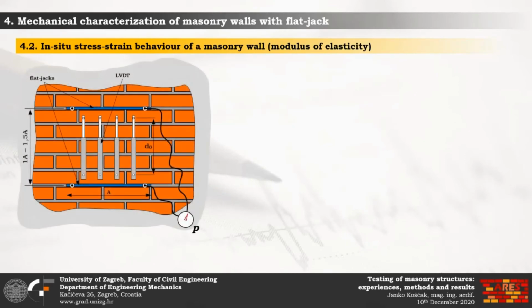Secondly, in situ stress-strain relationship behavior or modulus of elasticity can also be determined using the flat jacks. The procedure is shown in advance. Firstly, 2 flat jacks of a width A should be placed into the horizontal masonry joints, one above the other, at a vertical distance of approximately 1 to 1.5 A. In addition, the space between the flat jacks should consist of at least 5 layers of bricks, also as shown in the figure, and the flat jacks should be connected to the same hydraulic pump.